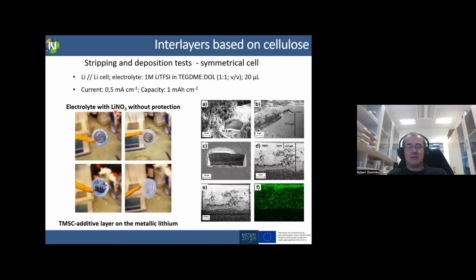And just to show you that this interlayer actually works, on the top is lithium metal, which was cycled in LiNO3 containing electrolyte without protection. We see this black surface. We see also protected edges, and we see intergrowth of metallic lithium into the separator. While in this case, we don't see any intergrowth of metallic lithium into the separator, we see some small damage, some small black spots. But when we look carefully with FIB measurements, we see that the silicium is still on the top, and this silicium comes from the silanized cellulose. But also there was a small growth or intergrowth of lithium during the deposition and stripping